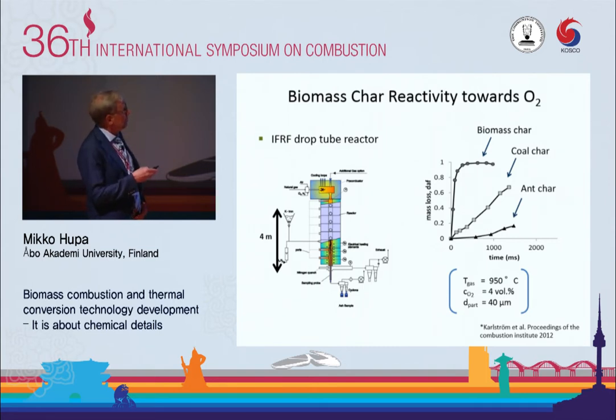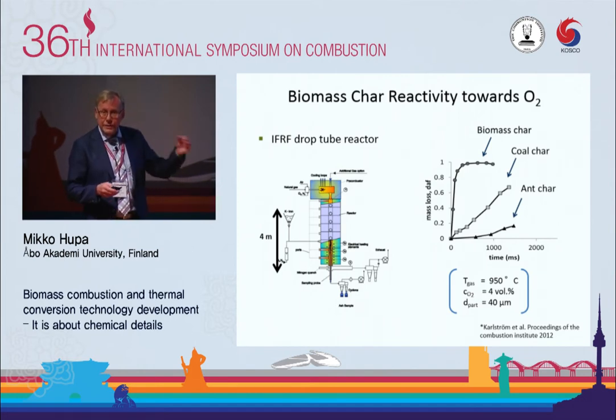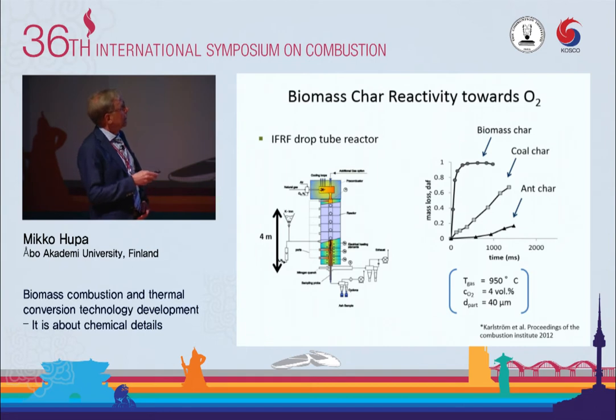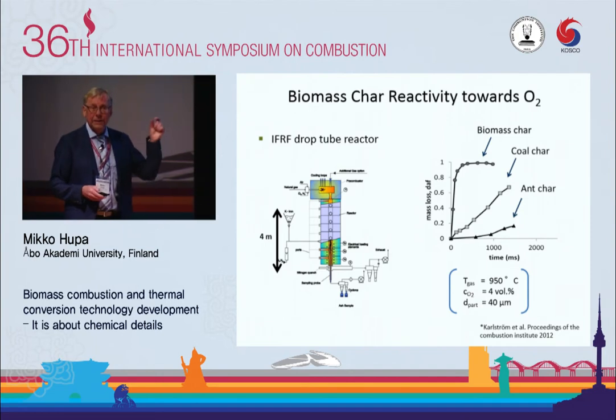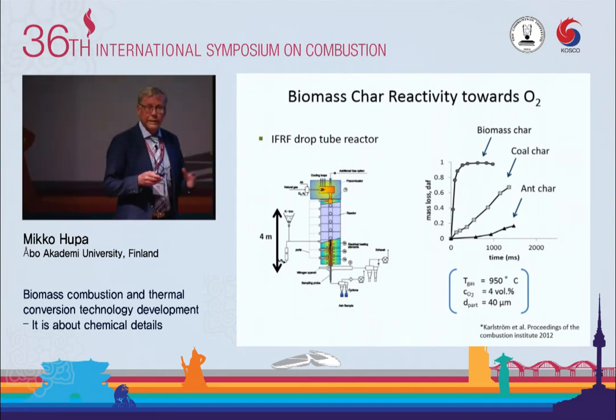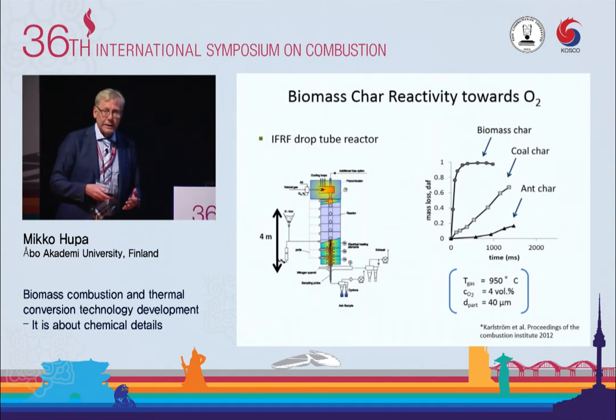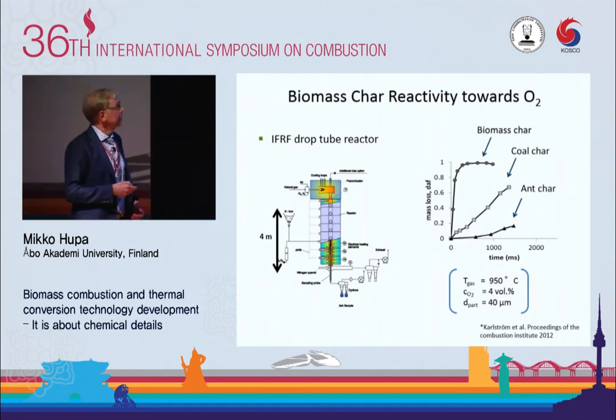Here are mass loss, or in fact carbon, char-carbon conversion for anthracite on one hand, bituminous coal, and biomass. The residence time, 1.5 seconds. This is just the char, so it's not the complete fuel. And you see that the anthracite char very little reacts, to a small degree, while biomass already can burn the whole char in this very short time. This is the same size, same mass of char, but the reactivity of the char is very, very higher for biomass.